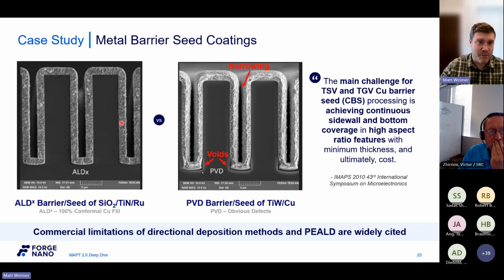Now, if you look at these two pictures, I promise you there are that same stack of ALD, but different composition. You just can't see it because it's an order of magnitude or more thinner. So here what we've developed is a silica process, a titanium nitride copper diffusion barrier, and a ruthenium, what we call a copper seed layer. So,